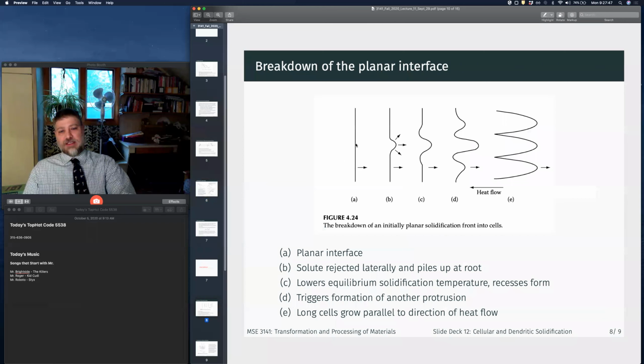But in this first picture, there's a concentration gradient in X, but it's uniform in Y. These are all growing by atomic jumps, so it's a stochastic process. At some region along here, you get a spot with a few more atomic jumps than its neighboring spots, and you get a very small protrusion that forms. This little hump has a tiny bit more driving force to grow than the surrounding interface, so it starts to grow out faster and faster. As it does that, it rejects solute not only in front of it, but to the side. So at B, we now have a composition gradient going both in X and in Y.